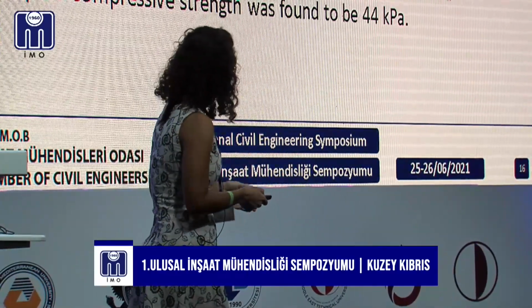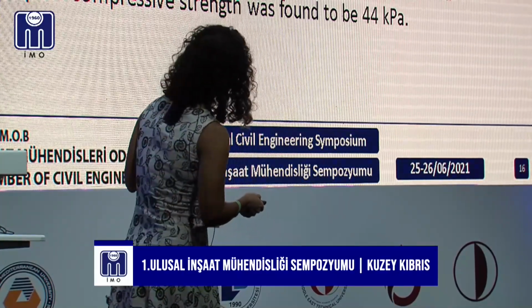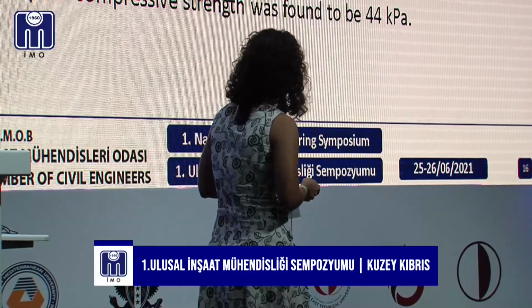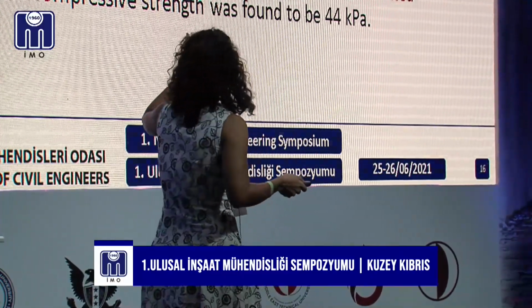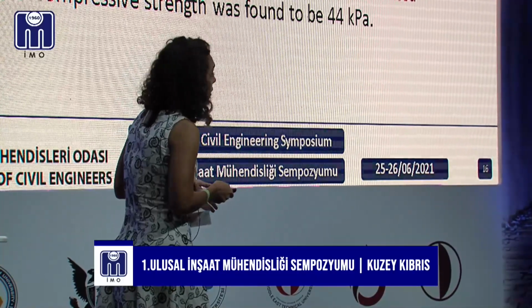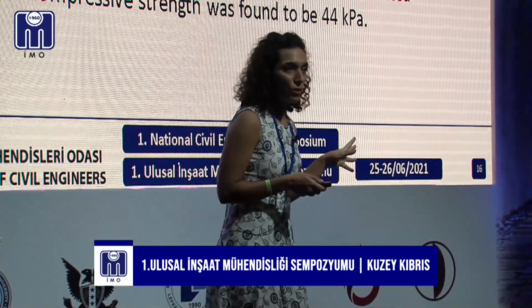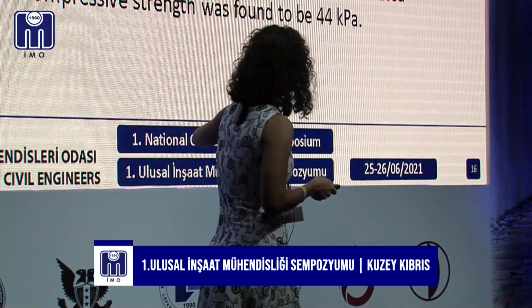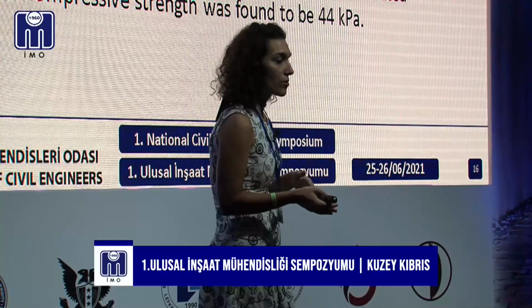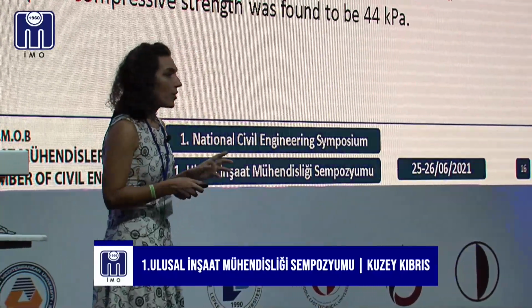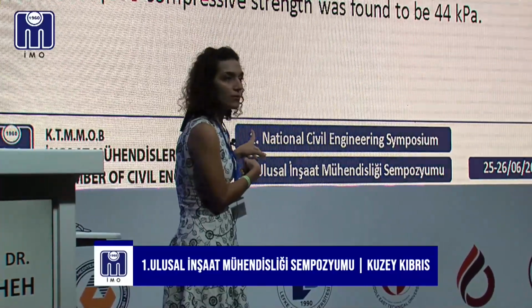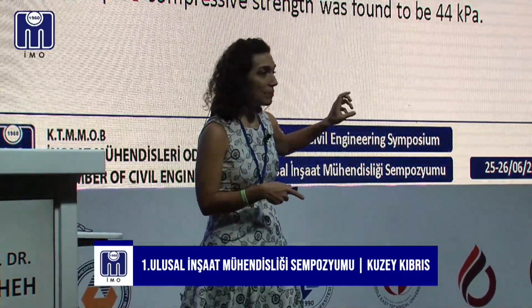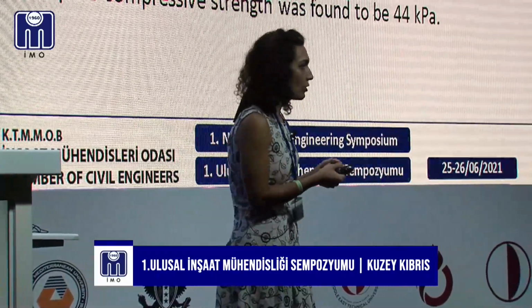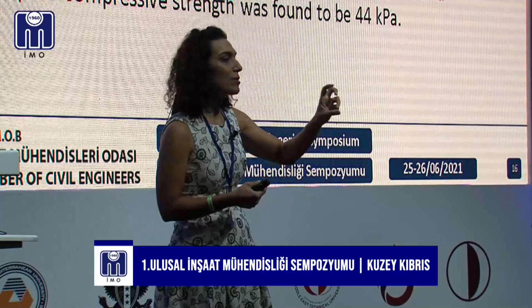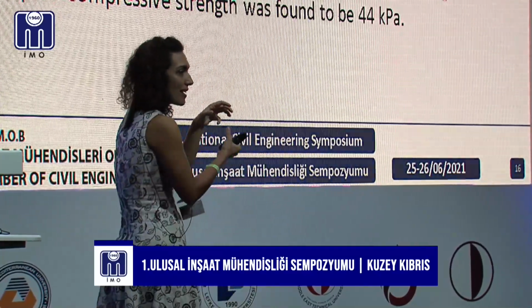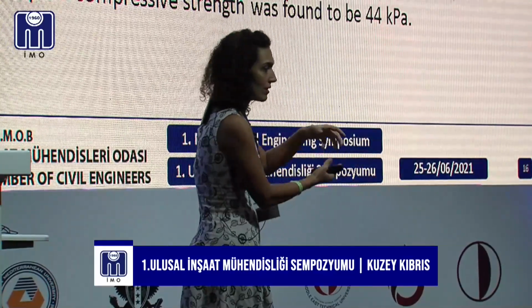So the soil sample was classified as a medium plastic clay, 49% liquid limit, 32% plastic limit, and plastic index of 17%. So optimum water content and maximum dry density was found using standard Proctor compaction test, and unconfined compressive strength of this untreated sample was found to be 44 kilopascal. So the point here is that usually for doing the unconfined compressive strength test, we use small samples. These samples have huge fibers in them, so we could not really cut them into small samples. Otherwise the samples wouldn't be identical. So we used the compaction mold as a mold for doing the test and prepare the bigger samples.